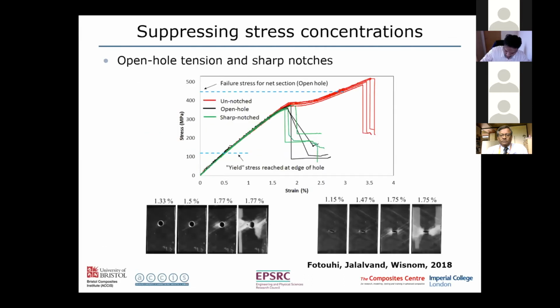One of the key features of this is that it produces notch insensitivity, because we can suppress the stress concentrations. If you have a hole or a crack, the stresses are very high next to that hole or crack. But this pseudo-ductile response redistributes load in the same way as yielding would in a metal structure. So in red, showing here, is the response of the unnotched specimen. And you can see that with the notch, whether it's a hole or a crack, we get up to the same point where the yielding starts in the gross unnotched specimen. But in this case, that allows us to get right up to that pseudo yield stress without failure.